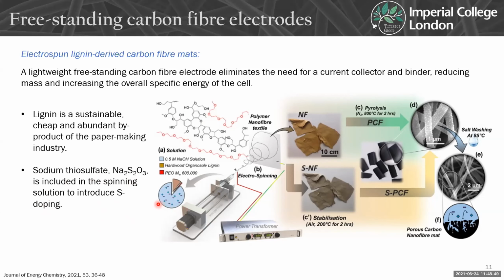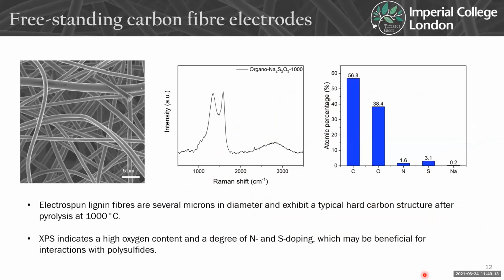Just as a summary of what the spinning process is, we have a solution that is lignin dissolved with PEO in a NaOH solution, and then we electrospin the fibers. And then we can either do a stabilization step or skip that, and we can pyrolyze it at different temperatures under nitrogen. And then once it's washed, we end up with these porous carbon fiber mats.